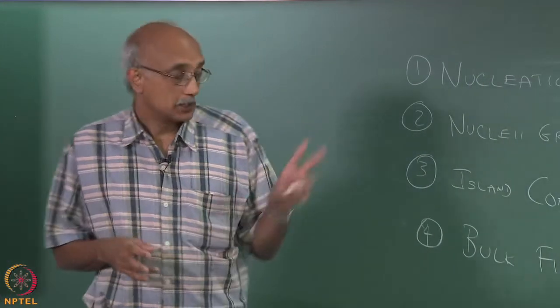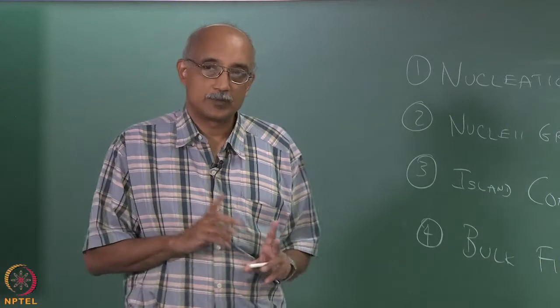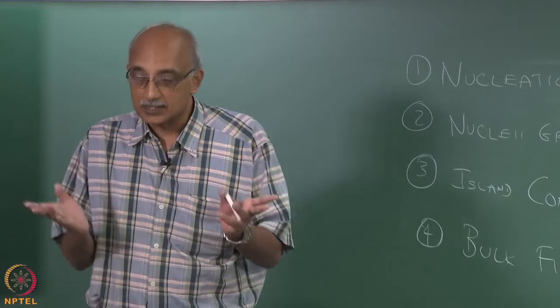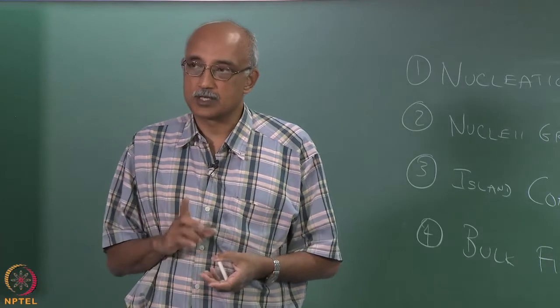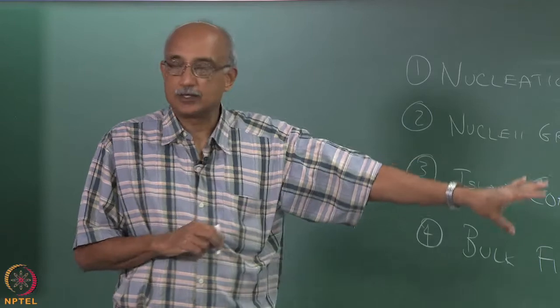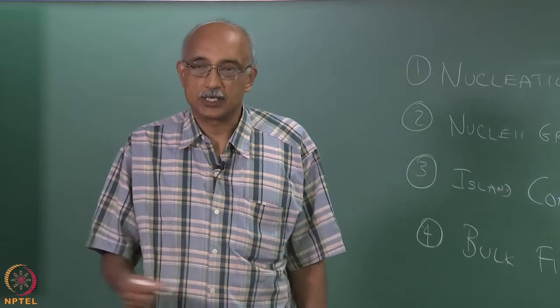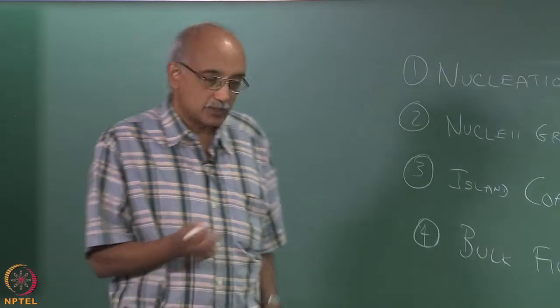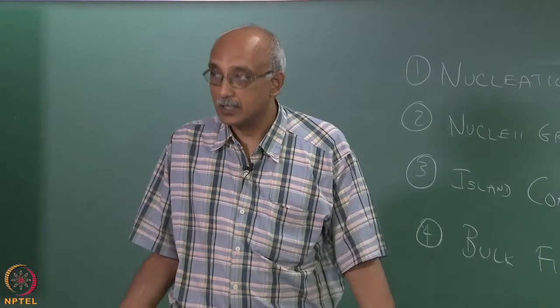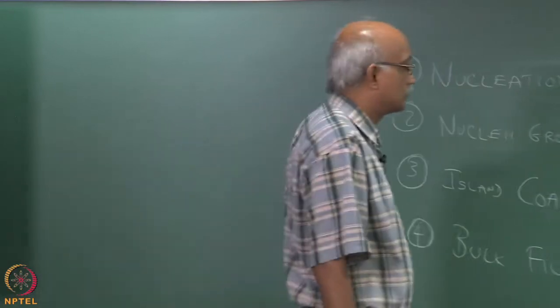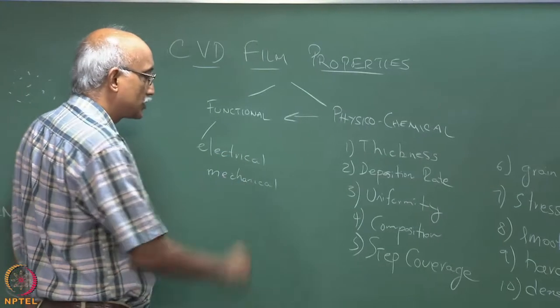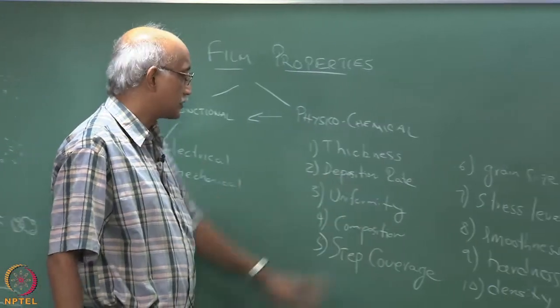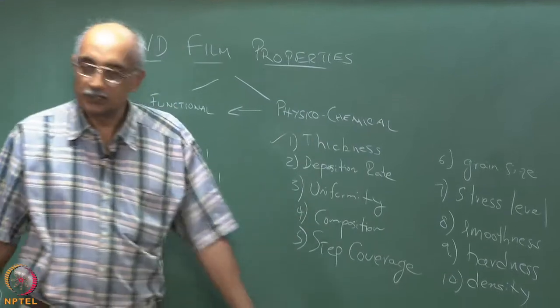So the functional measurements are actually easier to do, but the physico-chemical property measurements are important when you are first designing the process. When you're first setting up the process, you have to do the whole battery of tests in order to ensure that the process is set up the way it should be. But once the process is stable and running, you don't really need to do all these tests on a daily basis. What you would typically do for day-to-day quality control is do the functional tests, and then some subset of this. For example, thickness is measured on a daily basis, but deposition rate is not.